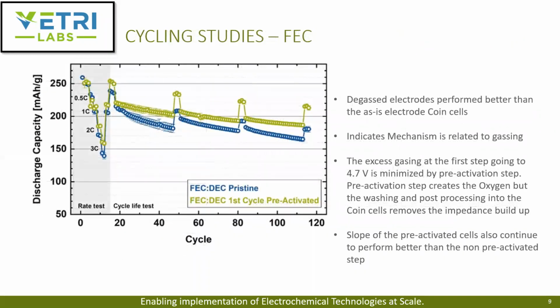On the cycling studies, this shows, especially with the fluorinated ethylene carbonate system, the blue dots are pristine, and the light green are the first cycle pre-activated. As we discussed, the first cycle is where they go to 4.7 volts. If we can remove the oxygen and remove the decomposition products, we should expect better results in terms of capacity fade if we can remove them and package them into a coin cell.